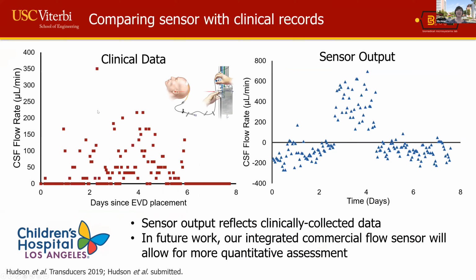And so this data here is that volume that is weighed. We've converted that into a flow rate, and we're comparing this to our sensor, which is running roughly at the same time. And so very loosely, we can say that we are capturing some of the outflow that is supposed to be happening. But the comparison is really not that great given the sort of low fidelity of data that we're getting from the clinical external ventricular drain. Also, you'll notice that some of the flow rate here went negative, and that's because these sensors were not properly temperature calibrated. And so we now have that circuitry in our system, and we're looking forward to doing the next study with this now both in animal and in patients down the road.